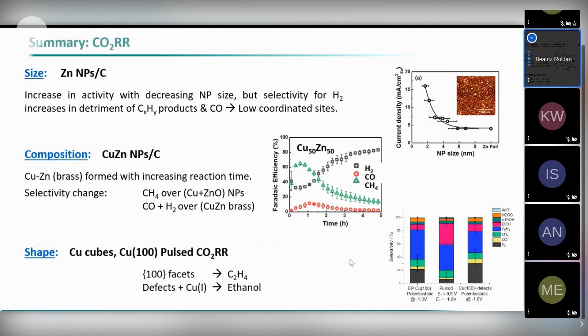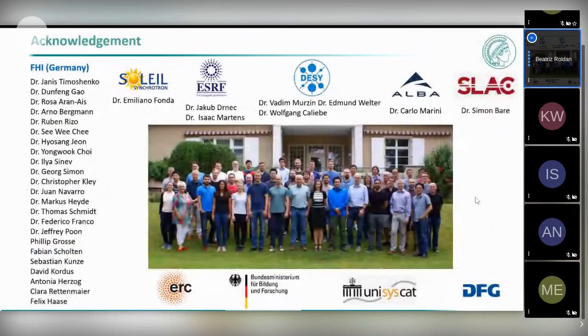And finally, I brought an idea of using pulse electrochemistry. In this case, we can do it to reconstruct the surface, and we can also do it to stabilize, for example, oxide species, in this case, copper plus species that are very difficult to stabilize when you are working at -1 volt. On top of that, you can also use it to regenerate your catalyst. If you, at some point under some conditions, you can get some contamination on the surface.